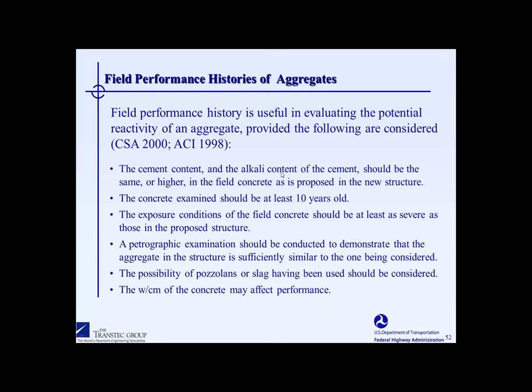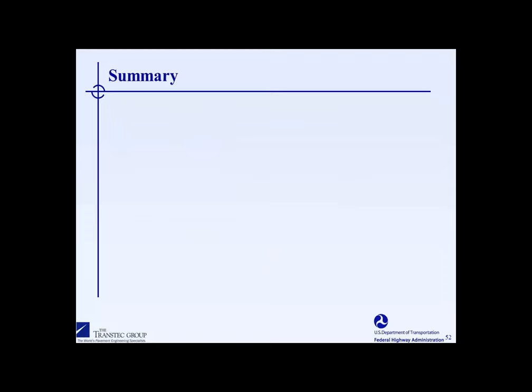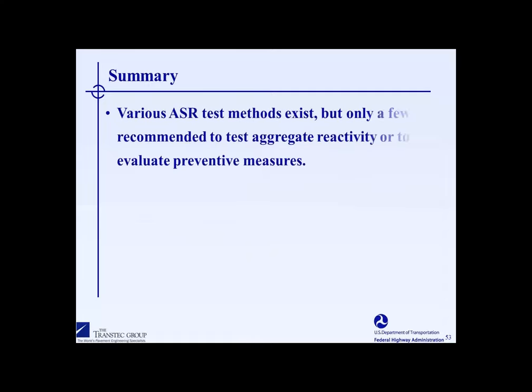It has to have the same cement content, the same alkali content. It has to be at least 10 years old. It has to have comparable or at least as severe exposure conditions. Petrography has to prove that the aggregate that's being considered is the same as the one for which field performance is available. The amount and type of SCMs has to be the same, as does the water to cement ratio. It's extremely rare that we can ever meet all of these criteria. But at least it gives us some guidance in trying to use field performance in a quantitative, predictive fashion.